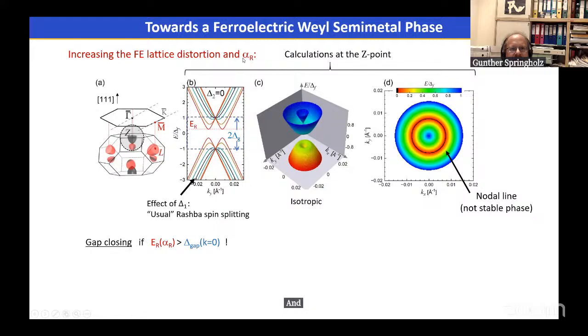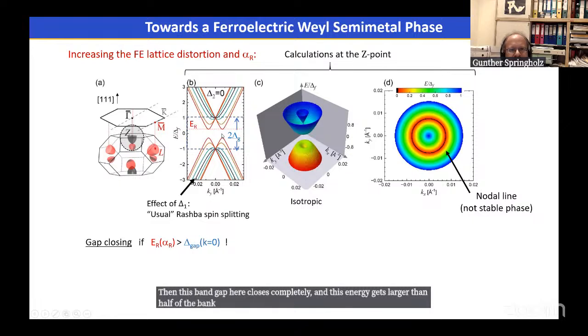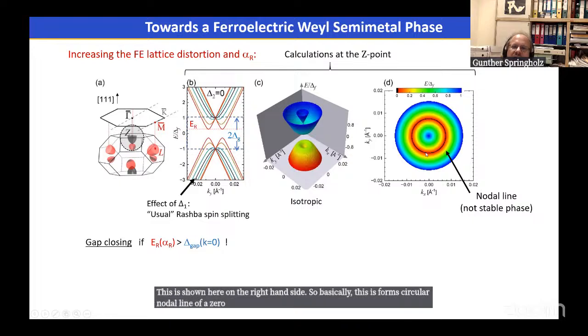And evidently, if alpha gets very large, then this band gap here closes completely, and this gap closing occurs if the Rashba energy gets larger than half of the band gap of the system. This is shown here on the right-hand side. So basically, this forms a circular nodal line of a zero gap semi-metal where the gap is completely closed.